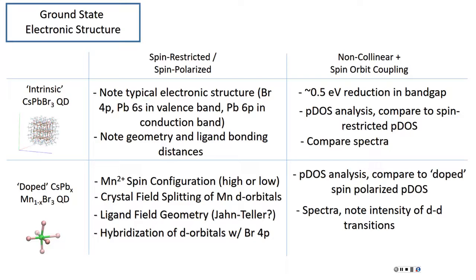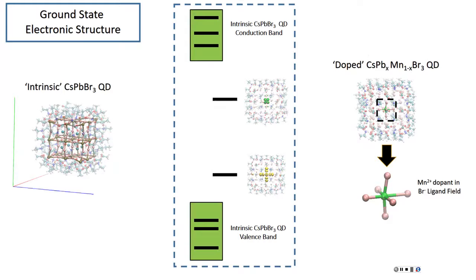Yes, there is a high probability of them to appear, but there are some tricks for the system that make it work. But the absence of trap states, going back to a previous slide, like here, there is your trap states, right? These black lines are doping introduced. But if you don't have doping, then the gap is open. You don't have any trap states. And this is because you really have nice ideal passivation. It's like a particle in a box, where you have the finite potential wells on the edge. So it roughly follows that idea. So electron density is inside the cube.